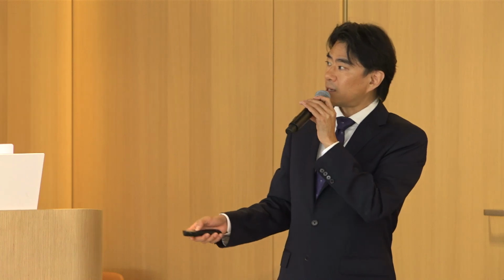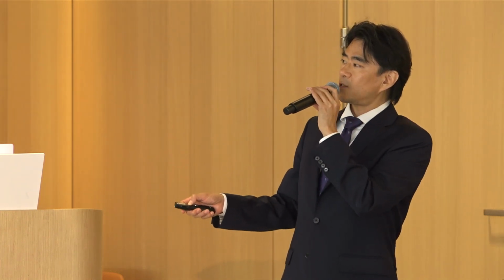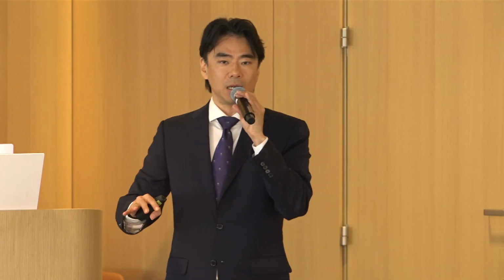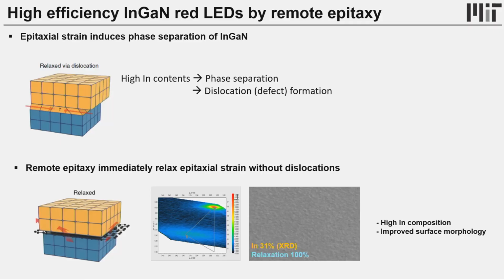It's super defective. Here at MIT, we understand that if there's a graphene in between when you do the epitaxy, then you can have spontaneous relaxation, meaning that epitaxial strain can be relaxed immediately. So then you can add a lot of indium in it. So we are looking at 100% relaxed, 30% indium in our single crystal indium gallium nitride on graphene. So then you can do the red. Currently, the crystalline quality is not very good, but we are working on this. We have a very unique solution.